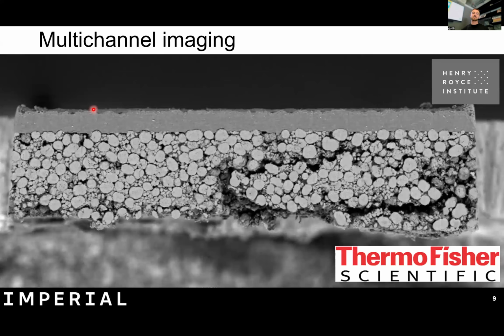This is indicative of the fact that the objects inside that crack are not on the surface. They're not on the imaging plane that's been prepared with a broad beam ion mill. This is very often something that we need to cope with in imaging porous media. We don't want the things that are in the depth to be considered to be on the imaging plane. Otherwise, that will mess with all of our statistics.